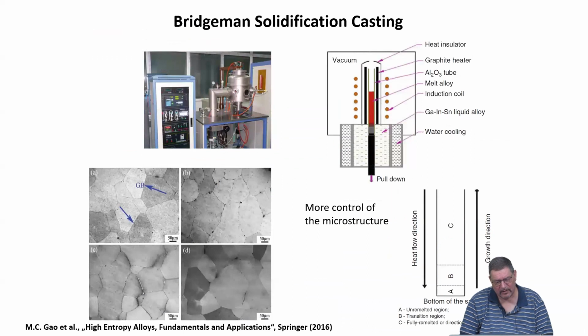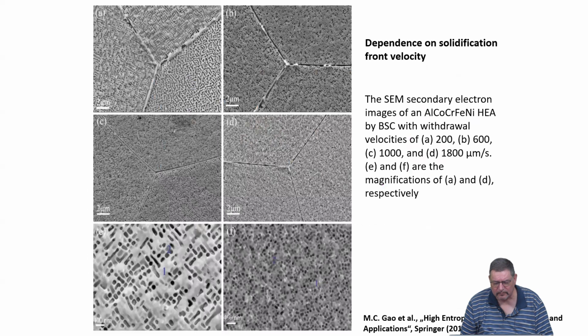Yeah, a very good method if you want to avoid these non-equilibrium artifacts is Bridgman solidification casting, which means that you basically pull the material from a liquid zone through a solidification zone and cool it, but cool it gently and not so quickly. So you have control over the speed of the solidification front. And that gives you normally good materials in terms of equiaxed structures, non-dendritic structures, good sharp grain boundaries, and also nice dihedral angles or tetrahedral angles at the junctions of grains, as shown here.